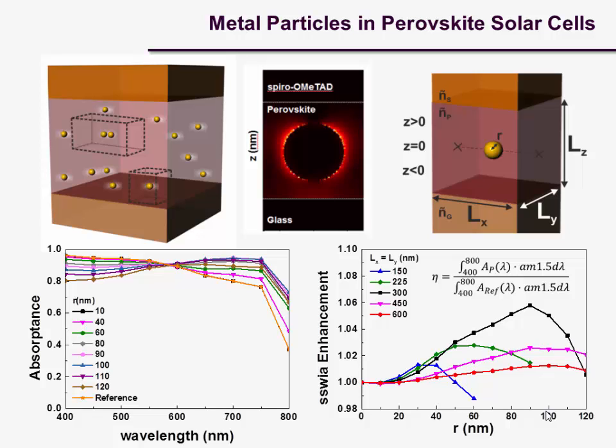this is not the electromagnetic field, this is absorption. So you have a contribution of absorption, to increase absorption both by near field effects and by scattering effects. And actually, we use this parameter, which I like a lot, it's very revealing, which is the solar spectrum weighted integrated absorption. So when I don't care anymore about the exact shape, I integrate everything, weighting it with the solar spectrum.